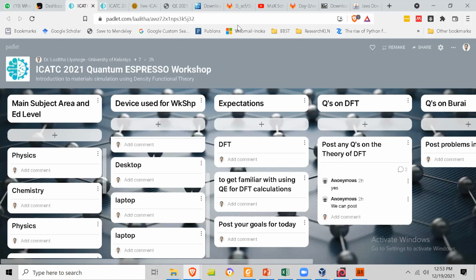Because let's say you want to use it as a semiconductor or whatever, a metal or a half metal. And there's a problem there also. You have the energy gap, and the energy gap is underestimated, right? In DFT, if you have strongly correlated elements like heavy metals in your system, then the energy gap is going to be not accurate. So you have to correct for it. Then you have to go to beyond-DFT methods such as ACBN0, DFT plus U, or the hybrid functionals or something like that. If you don't have any indication from experiment, that's what you do.